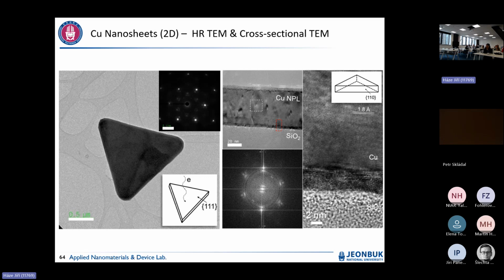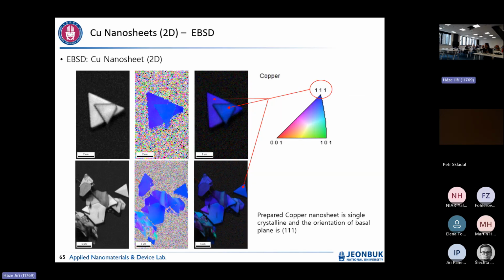Anyway, when you actually watch this one, this is 111. And when you carefully cut a cross-section of this one, this is the 110 plane. You can see it clearly in this image. And one more thing is we can measure the EBSD. This is one of the tools to visualize the crystalline structure. When you take an image here, definitely the base plane was only 111. So let's think, when you spray this on any desired surface, it is really easy to cover the surface because the dimension is really big, not nanoscale. When you cover 10 micrometers by 10 micrometers, you just need one 10 micrometer nanosheet, not 100 one-micrometer particles.